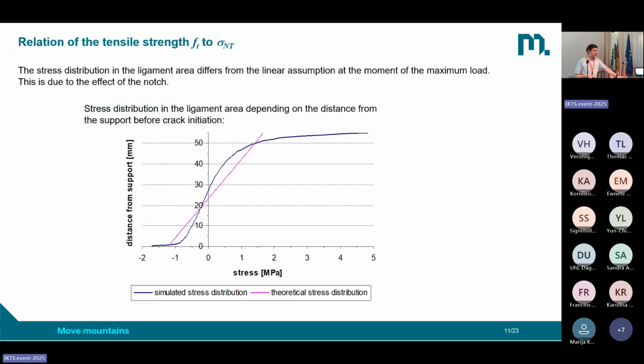Now the question is, you remember, we have been thinking, is this assumption for the nominal notch tensile strength justified or not, to have a combination of tensile and bending loads? And what we see here is the first part of the answer to this question. We see here the stress in the symmetry plane of the sample, and this is the bottom. Here's the support of the sample, and this is along this fracture surface. It means the crack would initiate here and then propagate downwards. And here we are at the moment where the crack did not initiate, so before the crack starts to propagate through the sample.